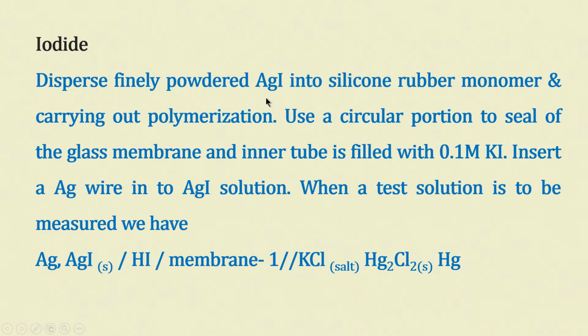So, the finely powdered silver iodide can be dispersed into a silicone rubber monomer, and polymerization should give me a silver iodide membrane. So, a silver iodide membrane should be useful for silver as well as iodide. So, I make a membrane and then cut a small piece, about 1 centimeter, fit it into the ion selective electrode bottom, and then the outer layer is my test cell, the inner layer is standard solution or saturated solution with silver chloride electrode as the reference electrode.